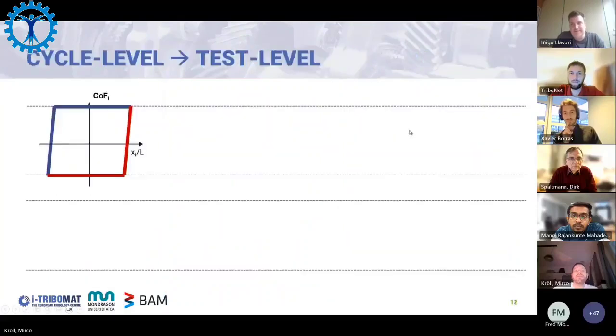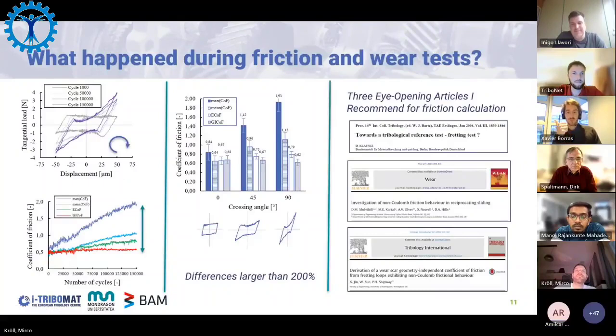Can I comment just about the effect of the compliance? In fact, there is an alternative method, which is to measure the compliance in both of the directions, calculate the average value, and after that correct the relative displacement using the value of the compliance. This is what I do, and just after I calculate the energy dissipated by friction. In my opinion, the best way is to measure exactly in the system what the compliance is, and correct the values of the relative displacement, because it's a linear equation, and just after calculate. In my opinion, it's the best method. Thank you. That's super. I agree. For the majority of cases, it's the best method for sure.